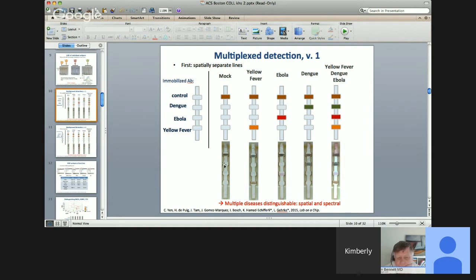Most importantly, if we run a mock sample that has human serum that has no biomarker for any of those diseases, we get no positions lighting up, which indicates that there's no non-specific adsorption. So this shows us that we're able to run a multiplex test for multiple diseases at once, and we can differentiate between them based on their position and color.